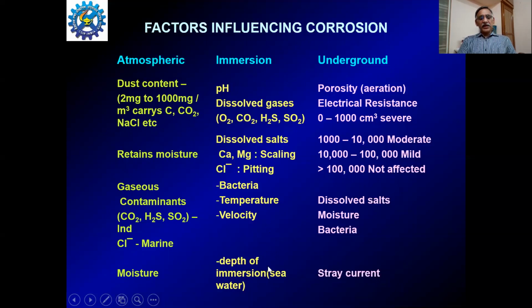And also in the case of the sea, it is the depth of immersion. For example, if a pipeline is kept in the sea, it will corrode at a faster rate because we have chloride ions there and a lot of oxygen. If the same pipeline is kept at the very bottom of the sea, it is almost corrosion free because the dissolved oxygen is negligible there. So this influences corrosion. Similarly, in the case of underground, that is buried structures, the porosity of the soil, which determines the aeration, influences it to a greater extent.